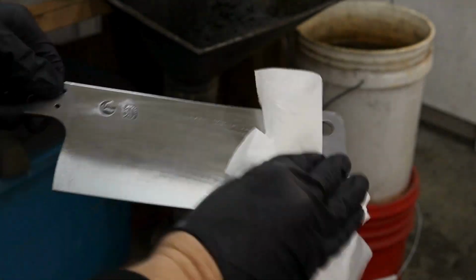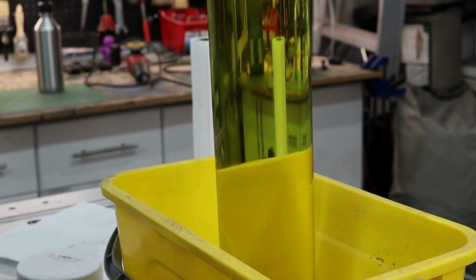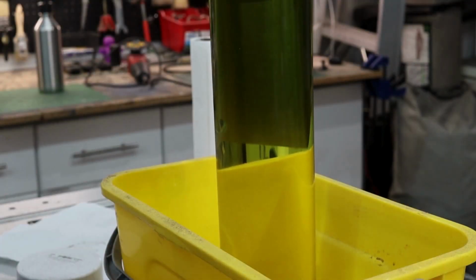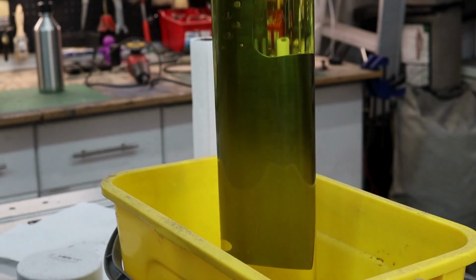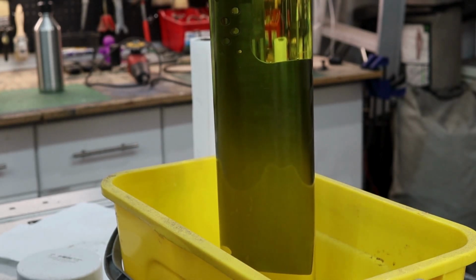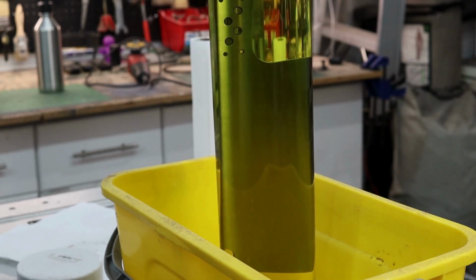After grinding the blade, I washed it well in warm soapy water to remove all of the polishing compound and then degreased it with brake cleaner. Just before going into the acid, I rinsed the blade in hot water, but I don't touch the steel with anything else at this point. Not my fingers, not a brush, nothing but water.